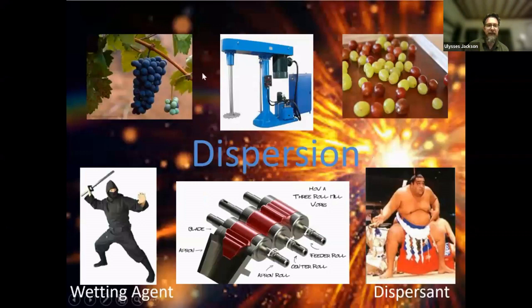So when we get pigments, they come agglomerated like a cluster of grapes. We start dispersing them with a disperser, and then it becomes single primary particles. To do that, we first use wetting agents, which are very low molecular weight surfactants that go in quickly and break apart the structures, allowing the milling to occur. So I like to call them ninja surfactants. And then we have dispersants, which are larger molecular weight surfactants that act as like bouncers or spacers that lumber in to those new interfaces and hold things apart.